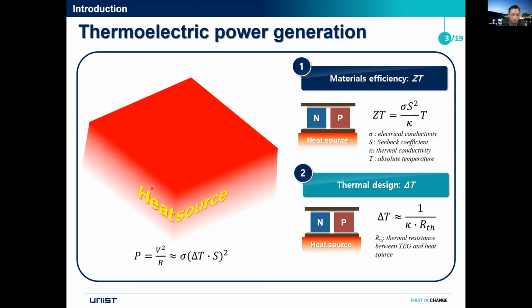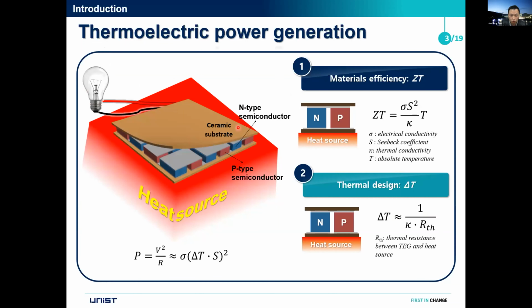This is the planar heat source. Once we contact this planar structured thermoelectric module on the heat source surface, thermal energy is transferred from the heat source to the thermoelectric material, and on the other side, heat is dissipated. This heat transfer and heat dissipation lead to the creation of a temperature gradient across the thermoelectric material, and then we can get power. And this power depends on the material properties, the electrical conductivity and Seebeck coefficient of the material, and delta T across the thermoelectric material.